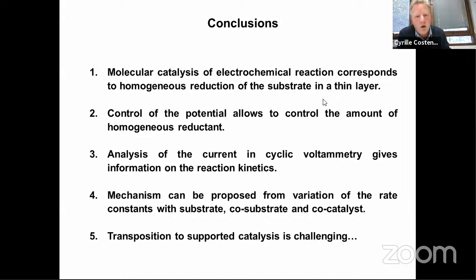Of course, you can also have information from the reverse scan if you observe new peaks, meaning that you have created new species. Again, you can also have information if you observe a crossing between the forward and reverse trace, which usually means that you have created a species which is actually a better catalyst than your initial catalyst. And then by changing the scan rate, you can get more information.